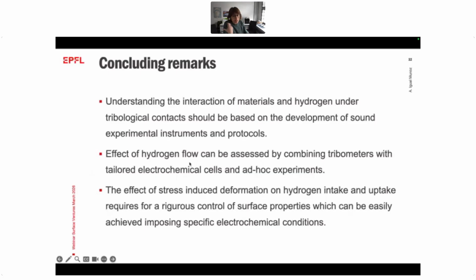So in any case, the hydrogen flow effect can be assessed with these tailored experiments and a specific permeation cell coupled to a tribometer. And then, of course, we can start answering the real questions about the effect of stress-induced deformation on hydrogen intake and uptake. And this, again, requires being aware that during testing, depending on the testing condition, we will have a certain surface with certain properties that can modify the outcome of the hydrogen-metal interactions.